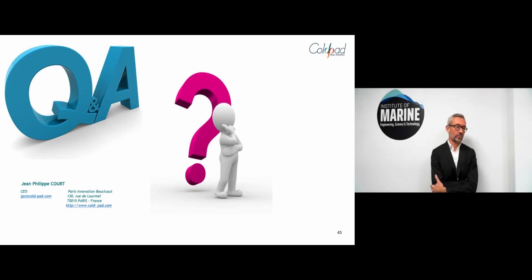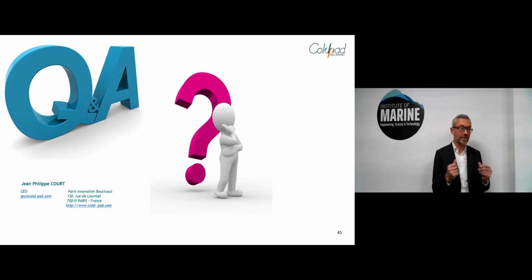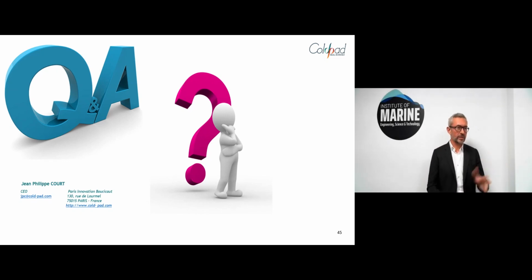Have you conducted any aging tests on the seal? Yes. We are, for the first products, definitely yes. We have done accelerated aging tests, meaning that we place a mock-up of the seal with reactive powder, so it changes color in case of detection of humidity of more than 50%. We place them over 3 years at a high temperature, 60 or 70 degrees, and we have frequent inspection. And with the Arrhenius law, you can do extrapolation.